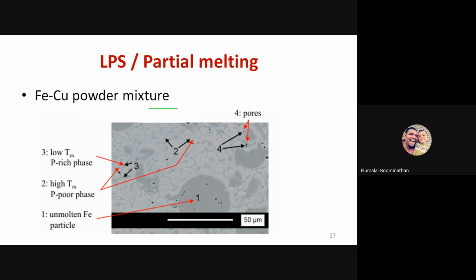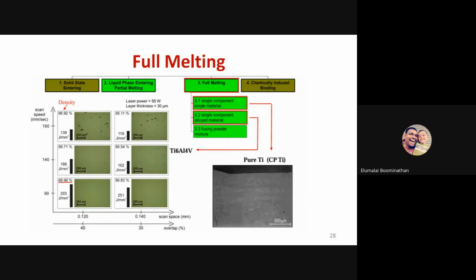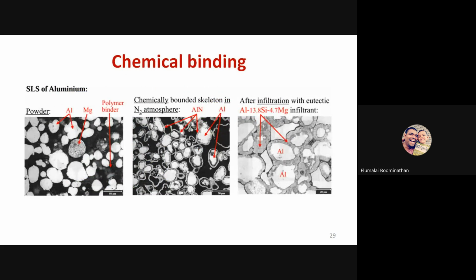You can see the same image. You have an Fe-Cu powder mixture. So the Fe is acting as a reinforcement like in a composite, and the copper powder makes the matrix here. And you can also have full melting. If you want to have a pure metallic part out of the PBF process, the powder is melted to its melting point, then solidified. So if you want a pure titanium, and there are alloys also, you can go for full melting. Full melting gives you a denser part. The porosity is an issue with all the PBF processes, where full melting almost reduces the porosity.